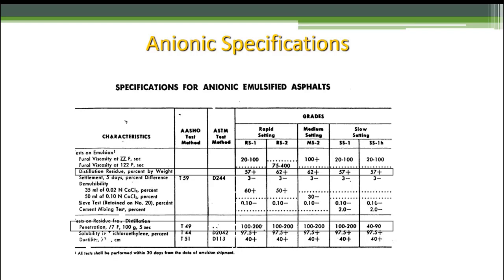And then on up the line. So a lot of times what we use is, okay, we need to shoot it heavier if we want so much asphalt on the road, and it's only 60% asphalt and 40% water. Guess what? We need to increase that shot rate to get that target of residual asphalt on the road. Important thing to remember for tack coat. Okay, we'll get into that a little bit later, and we get into it in the inspection class in detail.